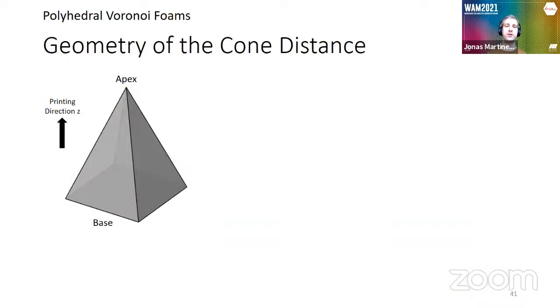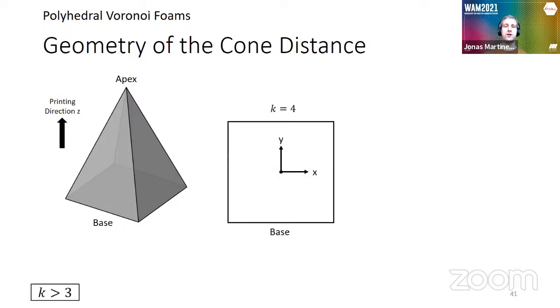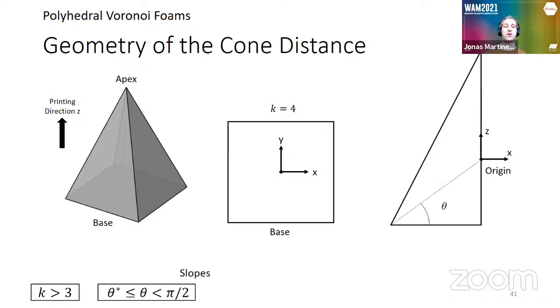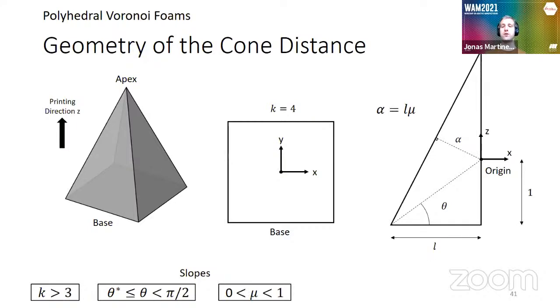So in 3D, what we did is basically to extend the idea and consider a cone that has some base. The apex is following the printing direction Z, and then, as usual, we get some parameters. The first is that this base is a regular polygon. So one parameter is the number of edges of this regular polygon. Then we have another parameter that controls the angle between the origin in the center and the base. Another parameter mu considers the ratio between the origin and the lateral side. And then finally, we have linear scaling that we apply in the x direction.